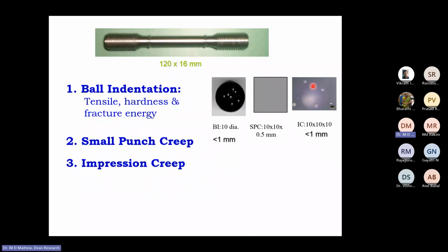And this one is the impression creep sample. It's again a 10 by 10 by 10 small block of material on which one can do a large number of impression creep tests. A small punch creep sample is typically 10 by 10 by half millimeter thickness. So one sample, one test, but the sample size is just 0.5 millimeter thick, 10 by 10. So this is the ball indentation test sample. This is the small punch creep sample, and this is the impression creep sample. And what you see here is the standard ASTM size creep sample. This is 120 millimeter long, 10 millimeter gauge diameter, 50 mm gauge length, and 16 mm diameter at the shoulder ends.